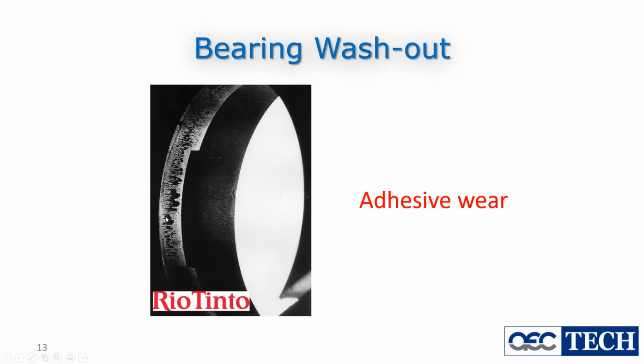This is a picture from Rio Tinto showing that the bearing has washed out because of adhesive wear. This area of the bearing is where aluminum is sticking and then moving, and when aluminum sticks, it sticks to the material and makes that thermo-compression bonding. Then when it moves, it grabs a little bit of the material from the surface with it. And then after a few extrusions, there might be some severe adhesive wear and washout in the bearing.